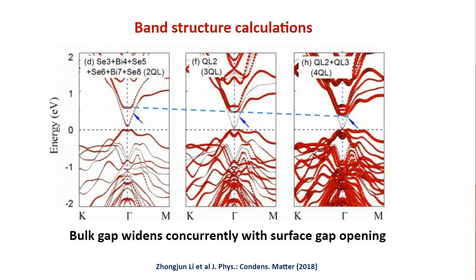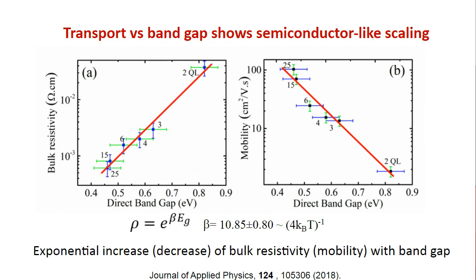Like I told you before, we are not sensitive to the surface state. So the band shown by this blue arrow, we are not sensitive to that, but we are sensitive to the band above and the band below it. That band gap is changing, and that's what we are measuring here. Later on, we actually confirmed this observation using transport also. We saw that the resistivity of this material also increased as we reduced the thickness. When the resistivity increases, it's getting more insulating, and more insulating means a higher band gap. That's what we are plotting here, showing that resistivity is exponentially dependent on the band gap. That seems to corroborate this observation that the gaps are increasing as you reduce the thickness.